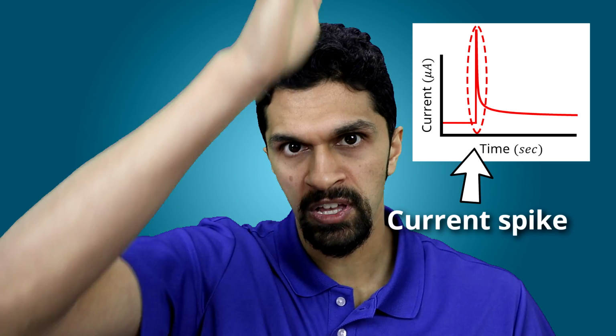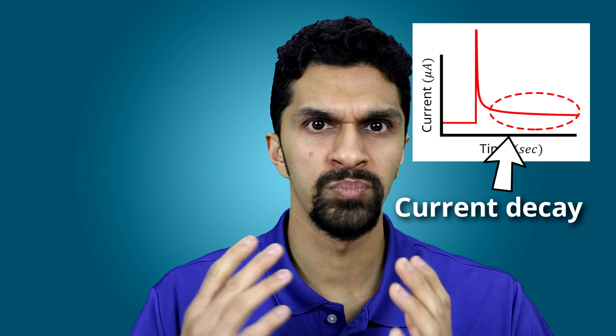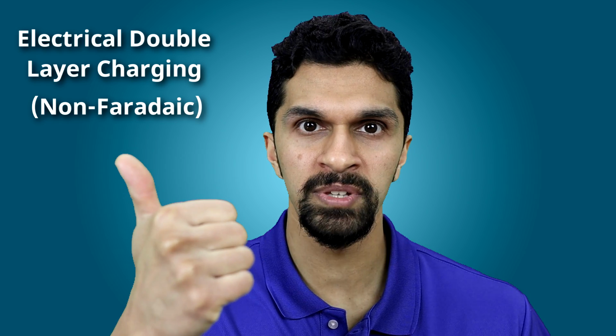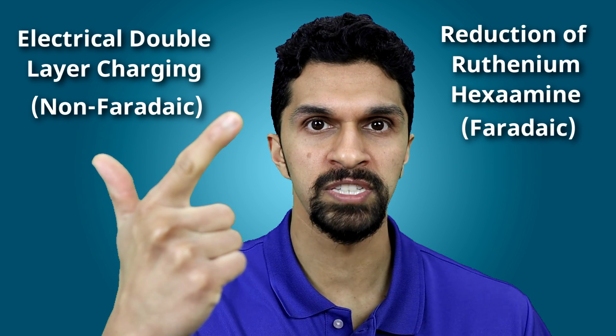When the potential is stepped, we observe this spike in the current followed by a gradual decay. Why is that? What processes are occurring on the electrode surface that give us this response? Well, there are two processes in particular that are responsible for this initial spike in the current. There is the charging of the electrical double layer and the reduction of ruthenium hexamine.